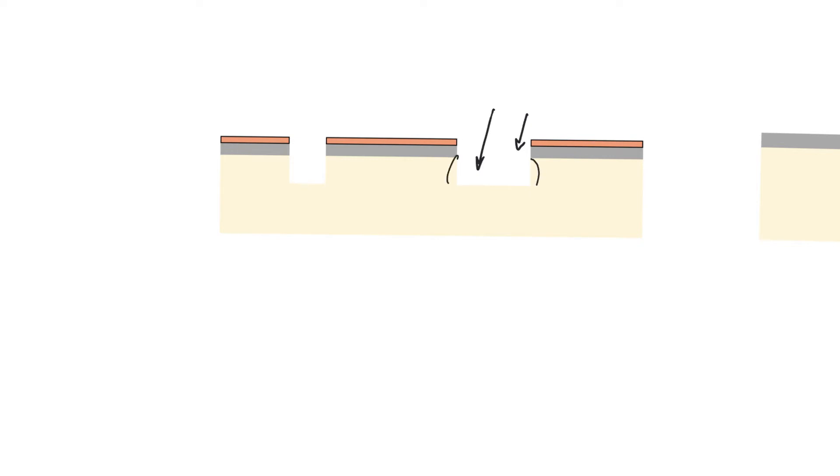Depending on the depth of the trench we create, which is of course going to be a function of the length of time we allow for etching, we would be doing either shallow trench isolation or deep trench isolation. Remember, one of the challenges of using wet etching is that it will create lateral etching. And so this will also eat up inside. And so that's a challenge in the fabrication of trench isolation.